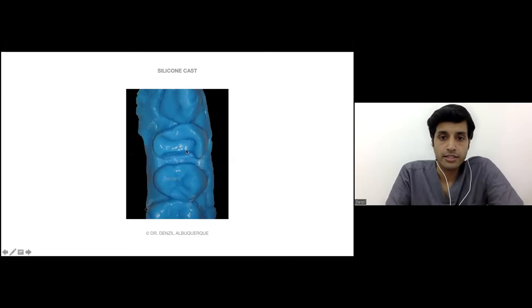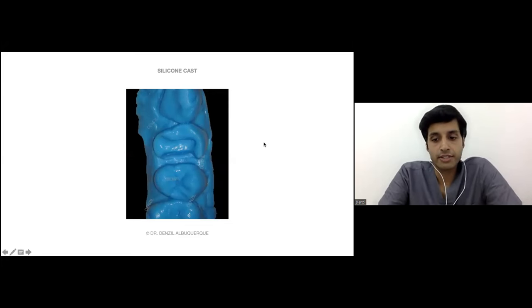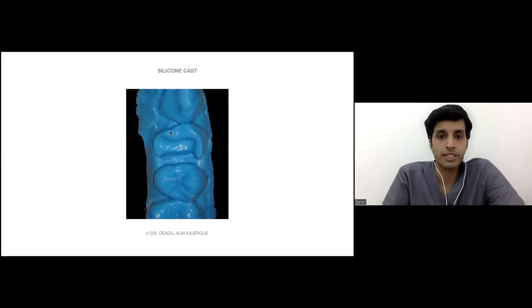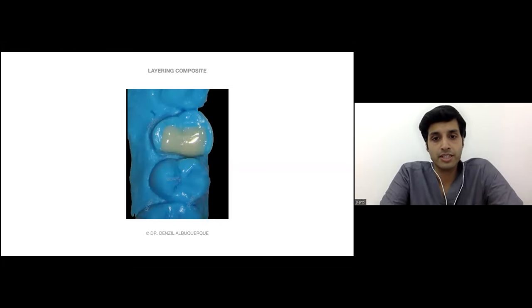And here you can see, once an impression was taken with alginate, this is nothing but a bite registration paste flowed into the alginate to get a positive replica of the tooth. Why is this done? The silicone does not stick to composite and it's immediate. It's just a 2 minute set. So chair side, we can pretty much do this. We fill it up with layers. I prefer not bulking it up in one go, multiple layers over here.